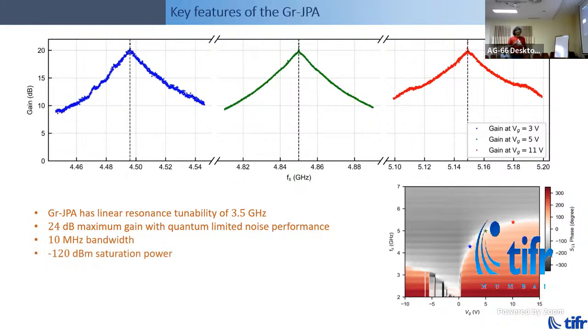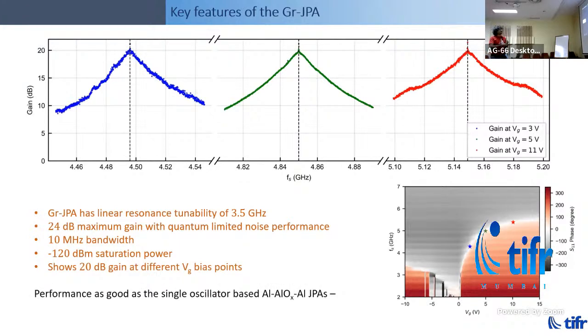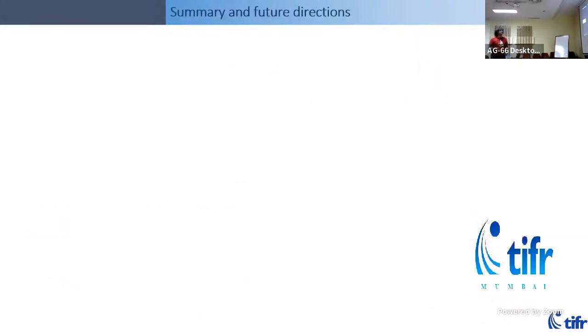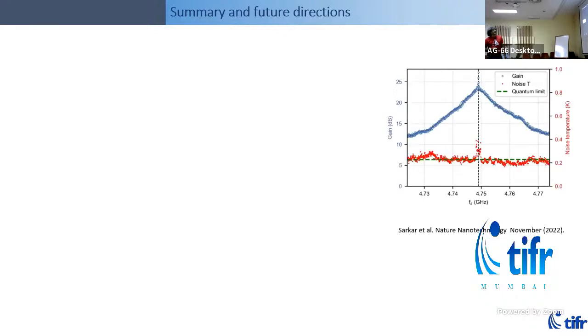And the bandwidth of this amplifier is about 10 megahertz, which is typical of these single para-amps. The saturation power is about minus 120 dBm, which is comparable to the aluminum oxide-based para-amps. So this performance is basically on par with the aluminum oxide-based para-amps, but now with a tunability with gate, incorporating graphene in their architecture. So I'm going to quickly summarize the key parts of this.